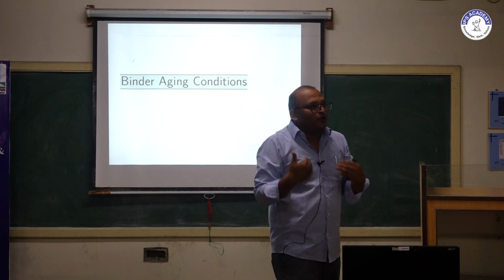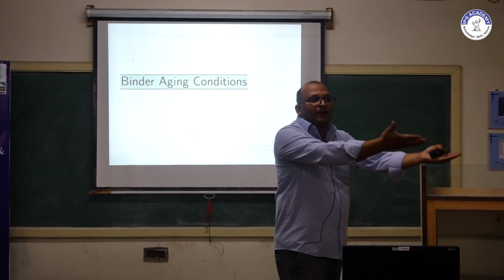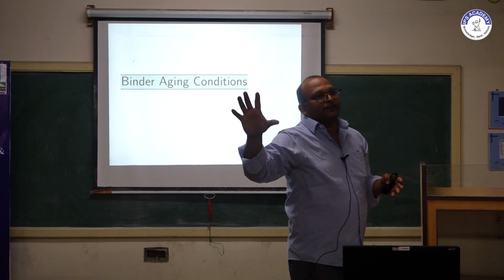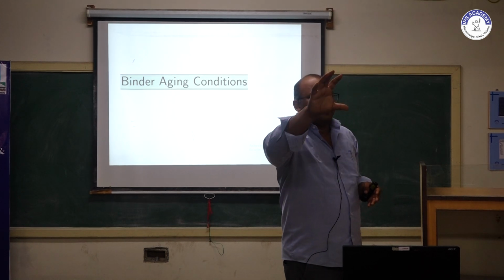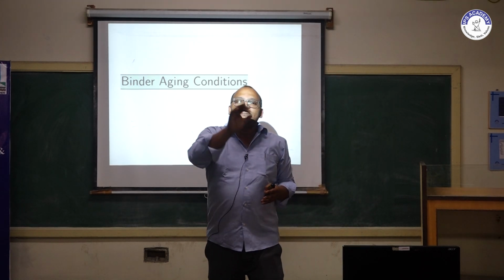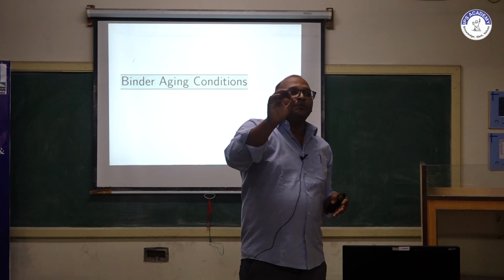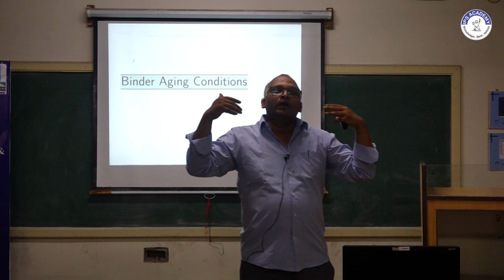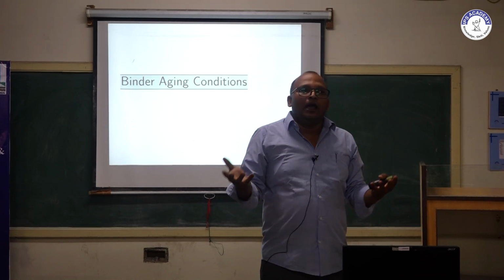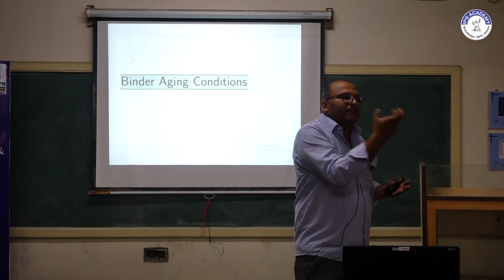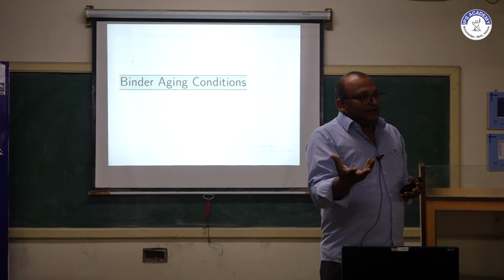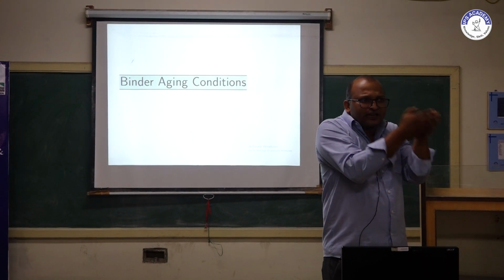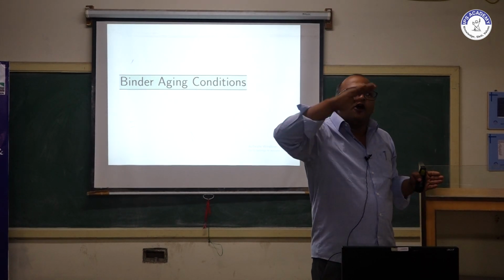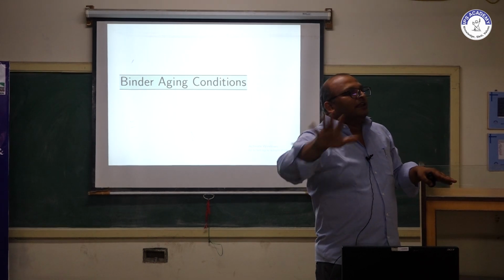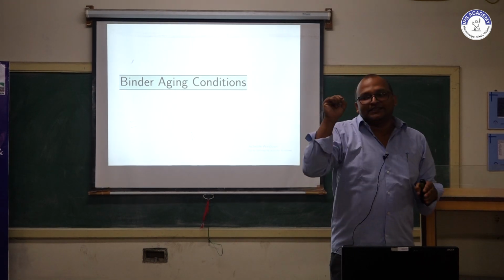And again, when you transport from the mixing plant to the field and compact, in this whole duration the binder will be at the elevated temperature. And you know binder has resins and saturates, that means some volatile elements. So if you heat it, some volatiles will be lost, and also at the elevated temperature binder may undergo an oxidation reaction, and that's how the stiffness of the binder may increase. So the first instance, starting from your mixing till the laying, compaction, till the cool down at the field, this is known as short term aging.